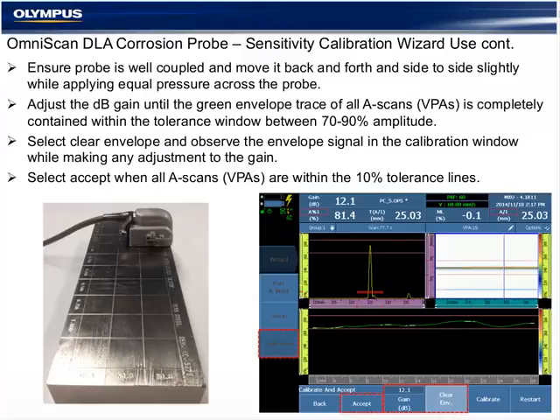This green trace represents the maximum amplitude detected at that time by each A-scan, so it allows us to see the amplitude of all A-scans. In this case, all of them are within 70 to 90%, which meets our 10% tolerance. When this case is true, it is not necessary to select calibrate.